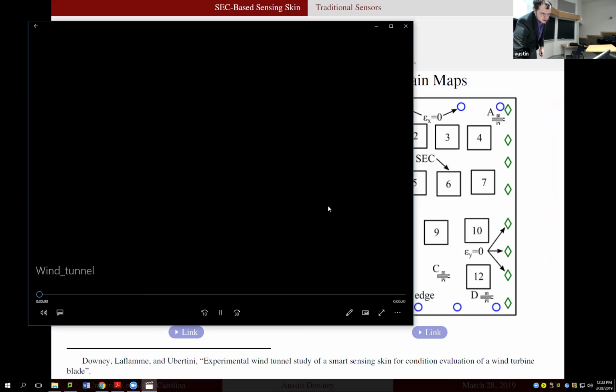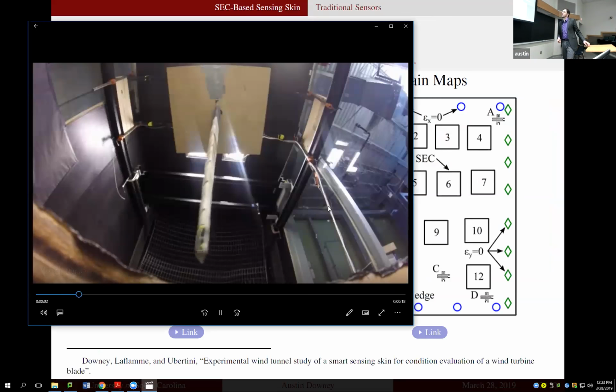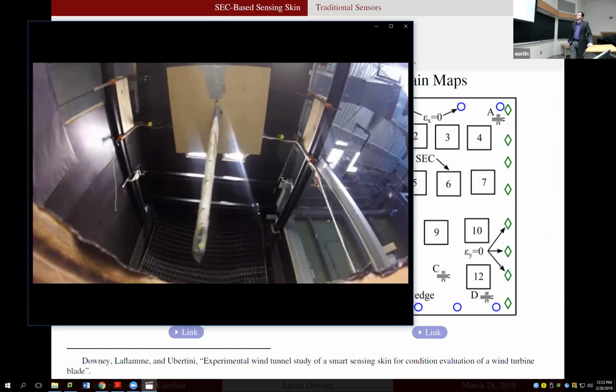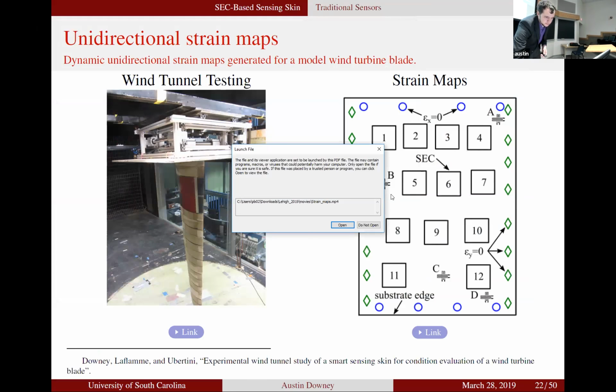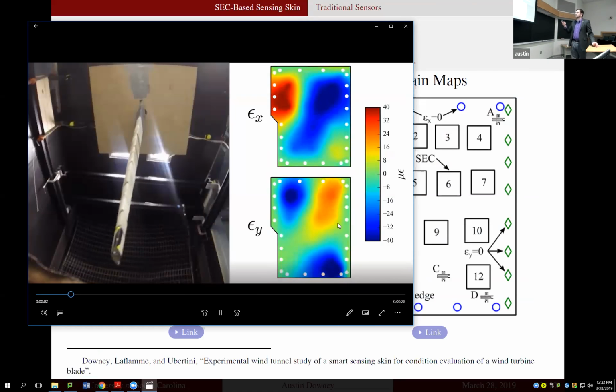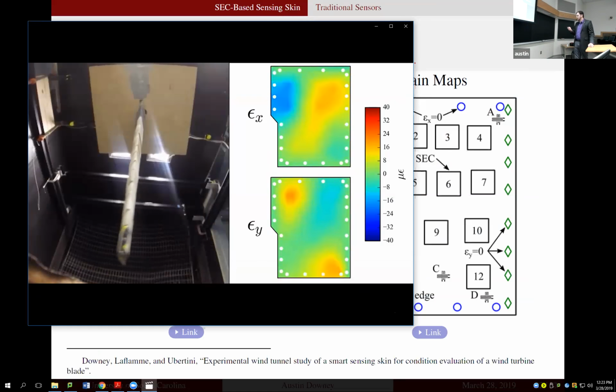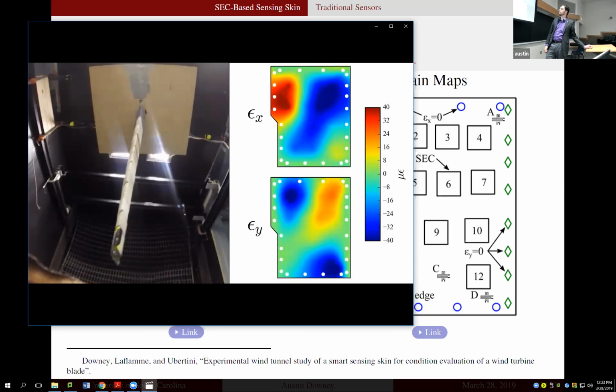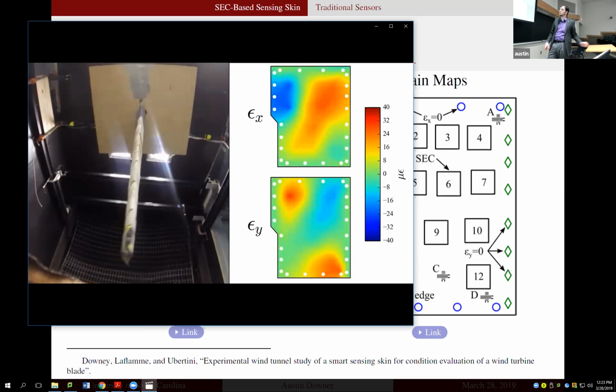And here's the wind in real time. So this is the blade operating in real time. Here's the wind blade kind of buffeting back and forth in real time. And then what we can do is take our SEC measurements and rebuild dynamic strain maps. So here we are slowed down, and we have epsilon x and epsilon y. Again, we measure the additive of the two, and we use an algorithm that we developed as part of my PhD to decompose them, but we haven't really discussed that here.